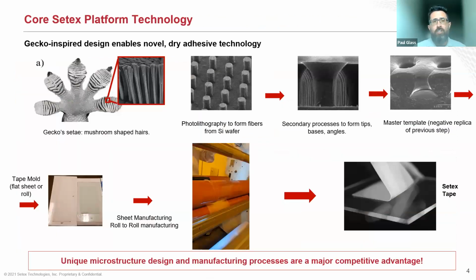So to produce our materials, we have a number of different products, but they all leverage the same core manufacturing IP, where we've taken methods adapted from the semiconductor manufacturing industry, and we can etch silicon into very highly ordered, predictable, high yield arrays with controllable diameter and spacing of a cylindrical unit. And we can take those silicon arrays, bring them to our lab, replicate them with soft materials, and do additive manufacturing processes that are highly scalable and high yield to control the tip shape, the base shape, the angle of those microstructures. You get a template that has very controlled, very predictable, very tunable adhesive or frictional properties.